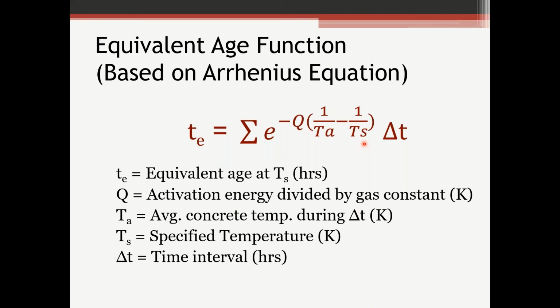Here's the equivalent age function. It's based on the Arrhenius equation. If there's any chemical engineers out there, the Arrhenius equation, I believe, is a way of estimating the speed of a chemical reaction. And if you think about it, that's kind of what we're doing here with the hydration of the cement and the heat of hydration. So T sub E is your equivalent age in hours. Q is the activation energy divided by the gas constant K. T sub A is the average concrete temperature during your interval, delta T. T sub S is the specified temperature, the temperature that is remaining constant. Remember, that's our laboratory temperature, or whatever temperature we're keeping constant.